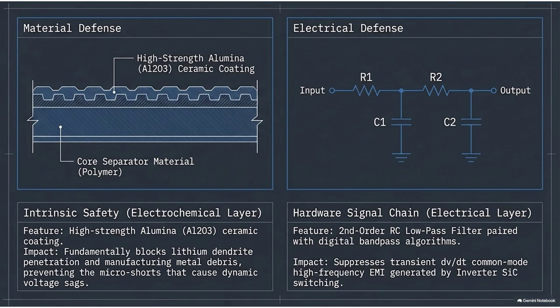Thermal stability. If a microscopic flaw somehow does create a tiny localized short, we know it generates intense heat. Right, the vaporization we talked about. Well, a standard plastic polymer separator will melt and shrink away from that heat source. When it shrinks, the tiny short becomes a massive hole, leading to a catastrophic thermal runaway fire. Oh, so the plastic makes it worse.